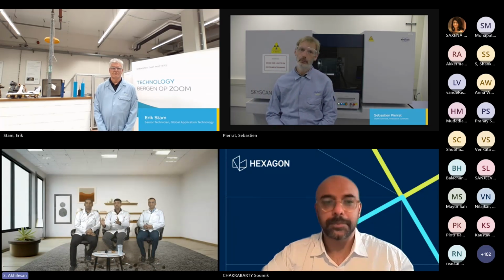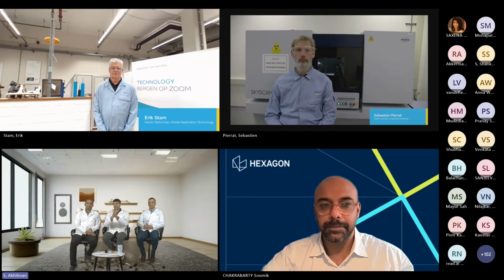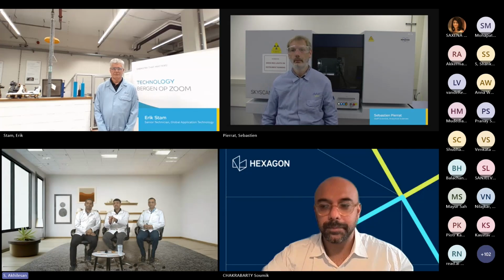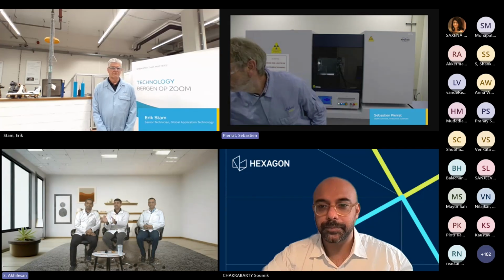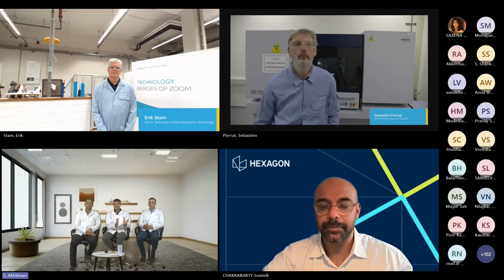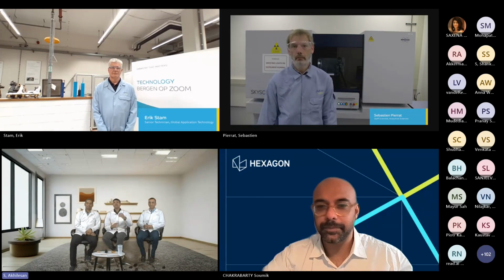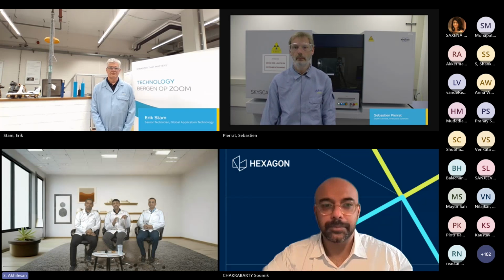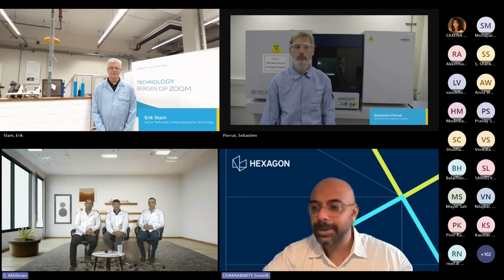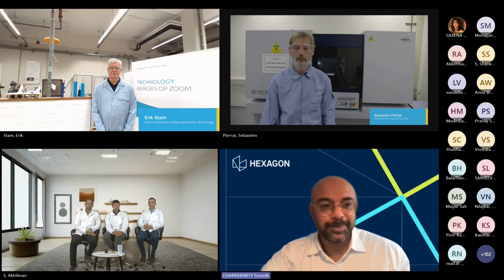So Digimat material models, if you give it a set of fiber orientation, it does the micromechanic studies and predicts what will be the local behavior. That's what the Digimat card does. But what the processing tool does is predicts for different thicknesses how that orientation is going to be. And that is very important to be calibrated in the mold filling solvers and not from the Digimat material cards per se. Okay. I hope that answered the question.